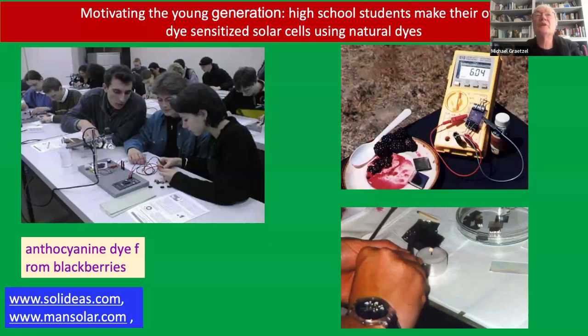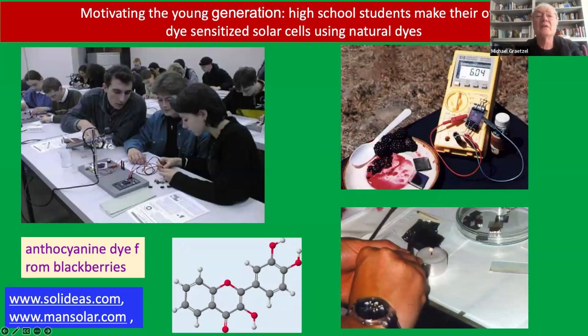And at the end, we have to motivate the young generation, and so the dye-sensitized cell is unique. You can have young kids make themselves a solar cell. You couldn't do this with silicon or even perovskite. So the dye-sensitized cell is simple. The only thing you need is a source of dye, and you can use berries, for example blackberries, raspberries, blueberries. They have this anthocyanin dye, and you see the two hydroxyl groups. They attach very firmly to the TiO2, so they form a self-assembled monolayer.